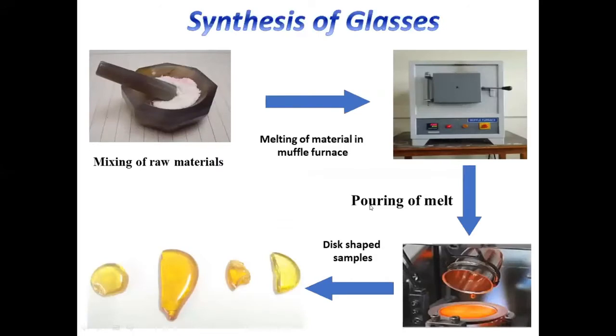So how to prepare glasses? You can start with your oxide materials. With a mortar and pestle you just mix the starting materials. And this is the platinum crucible, which shows the melt. And we put these materials in a furnace. We melt them at a temperature of about 1000 degrees Celsius. If these are silicate glasses, you may need 1500 degrees Celsius or 1400 degrees Celsius. And then we pour the melt and we get these glass pieces.